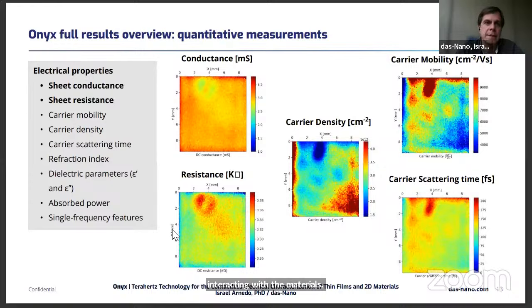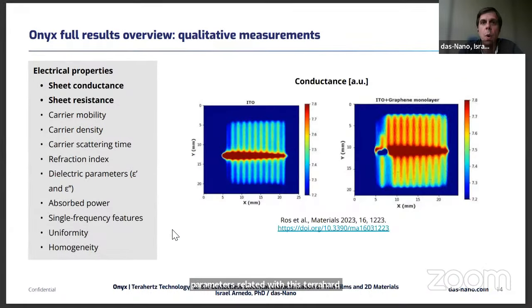We can measure several parameters in a quantitative way: conductance, resistance, carrier density, carrier mobility, carrier scattering time, refractive index, dielectric parameters, absorbed power. So many parameters related with these terahertz signals. And we can also give you qualitative measurements. So we are able to give you uniformity, homogeneity. So it's a tool that serves you to quantify, but also to have an idea of your production process, the evolution of your production process.